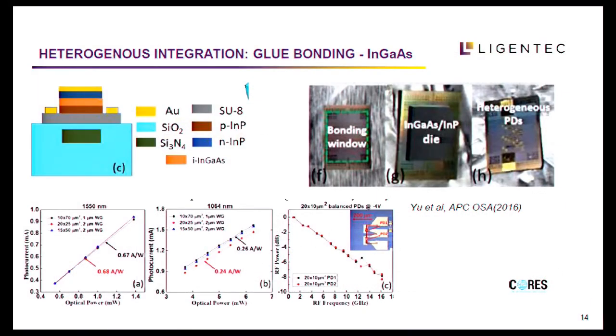Now, we can do glue bonding. And in the case of glue bonding, you can see that there is the addition of the glue layer here. This is an SU8 layer. Again, this work is done under the DARPA CORES program. And there is this bonding window, and then you bond your indium gallium arsenide, indium phosphide chip to it. And you do all this post-processing to put all the electrical contacts we said before. And if everything goes well, you get a photodiode